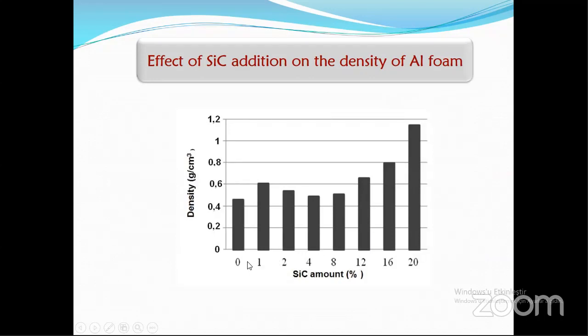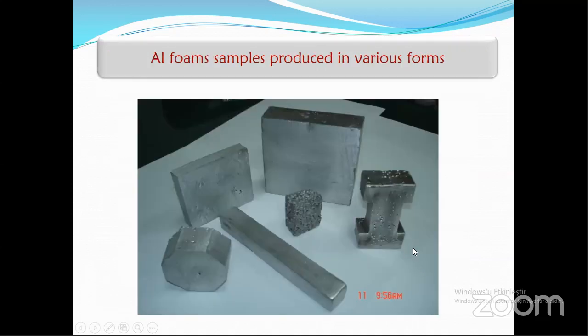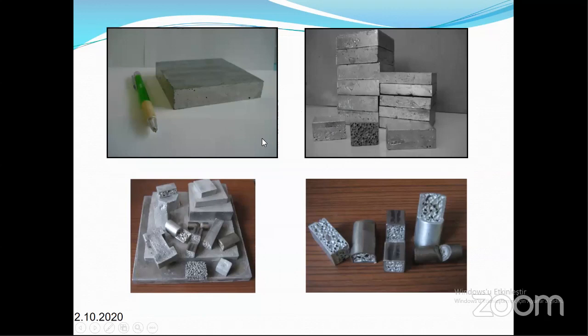This is the density of aluminum foam, depending on silicon carbide addition. That's the 0%. At 1%, the density is 0.6. At 2, 4, and 8% about 0.5, and then it starts increasing. This is the aluminum foam sample produced in various forms. Actually, we produce lots of samples. These samples were also produced in our labs. Those are the conventional samples, sample profiles, and tubes filled with aluminum foam.